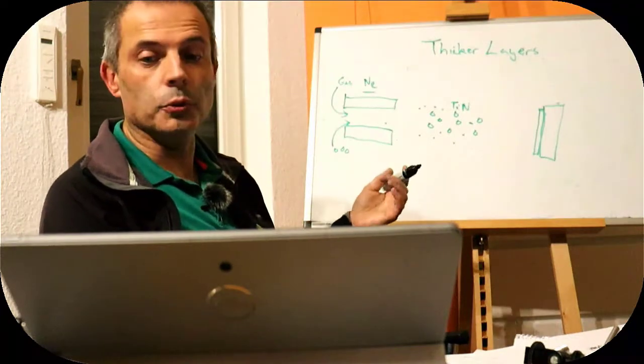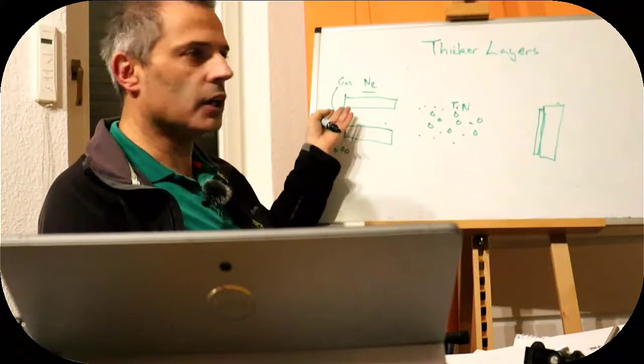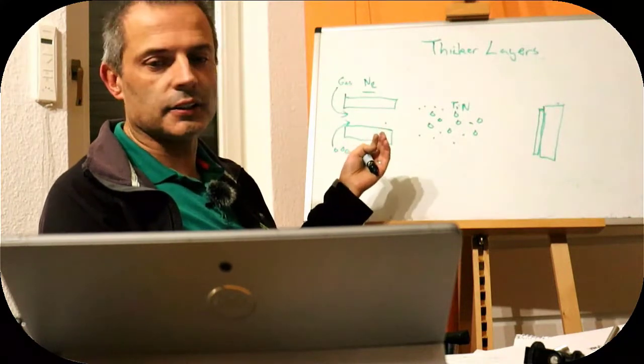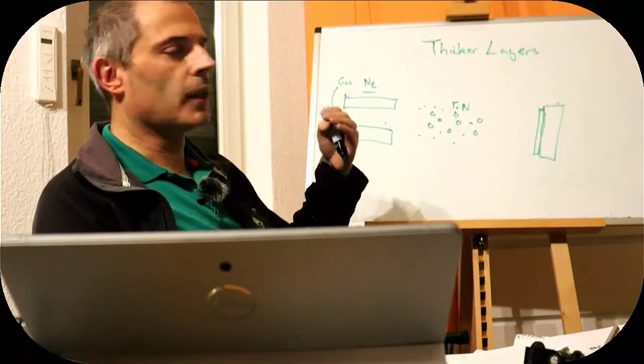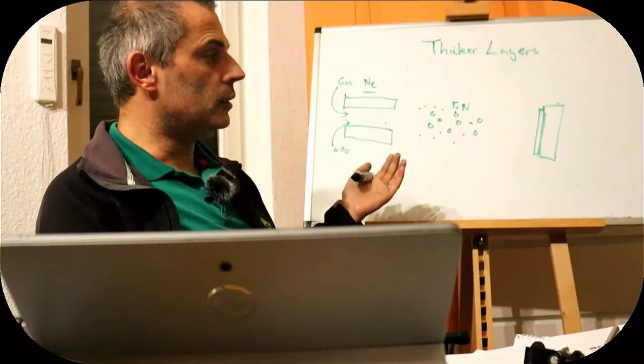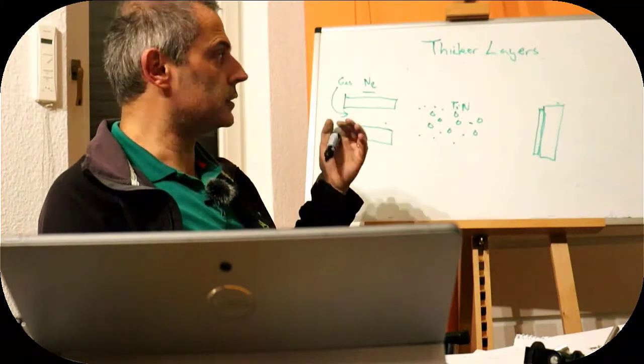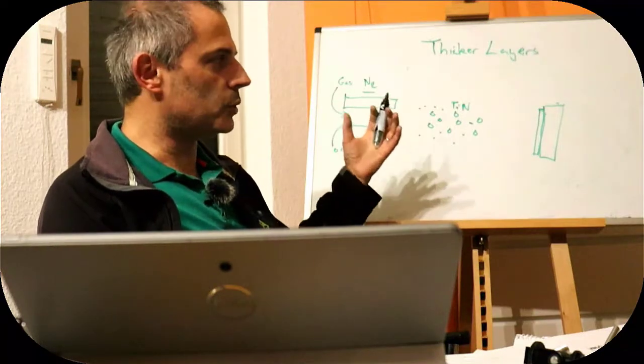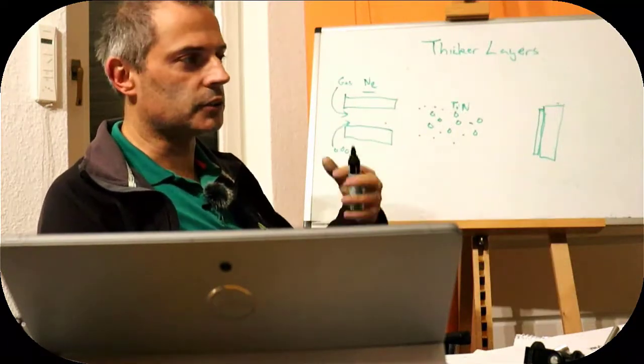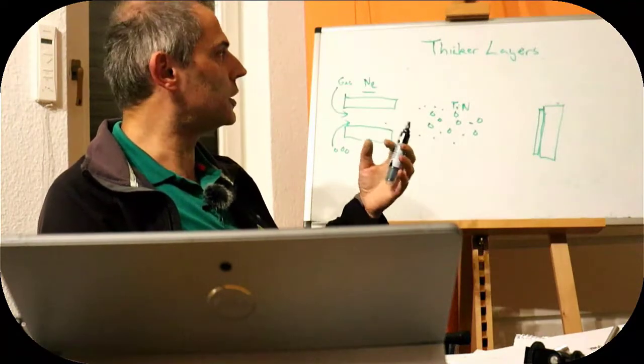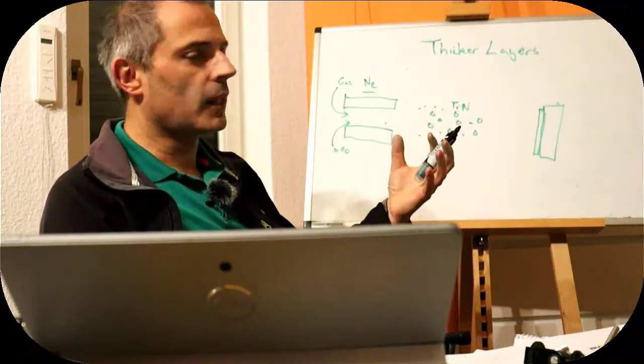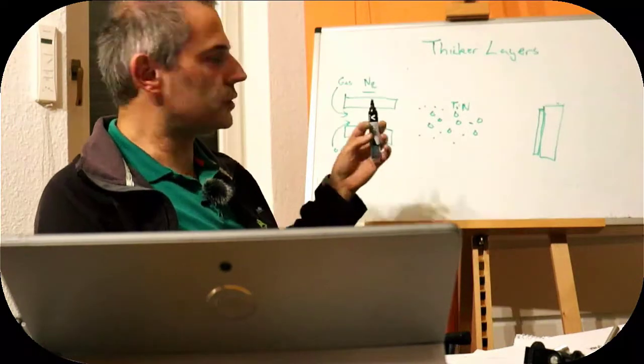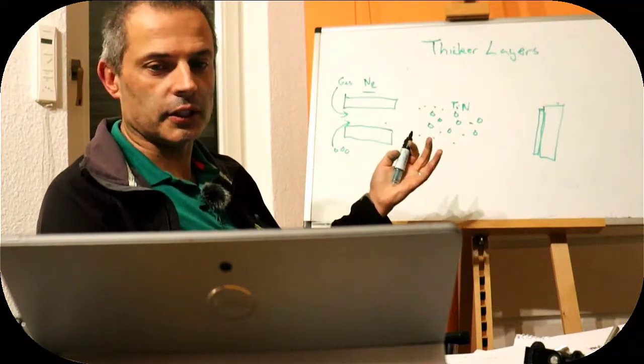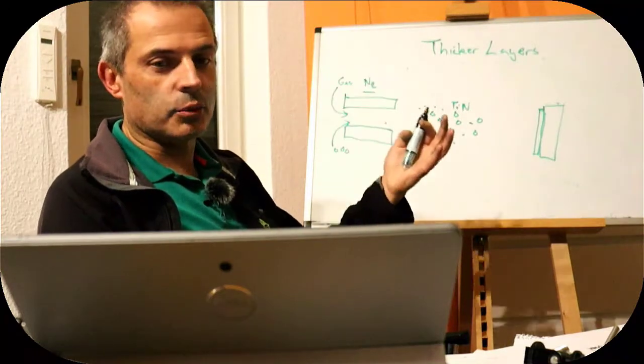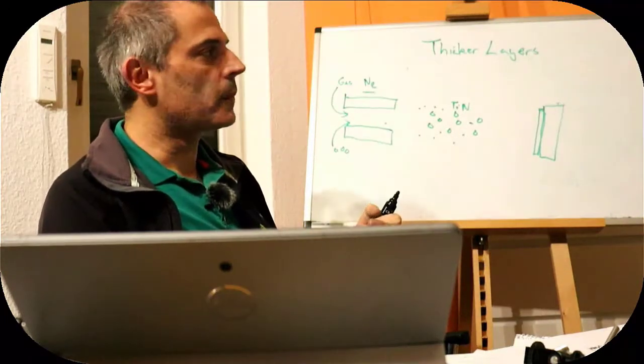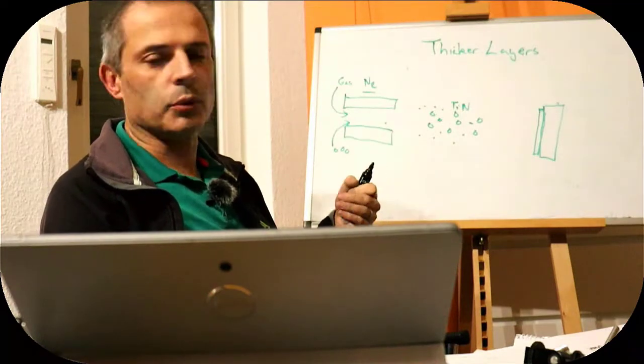So typically you would have thought, looking at this, what we want is argon in our gas, and that is a terrible gas for this. If you know anything about launching things into space from guns, or high-speed guns, multi-stage guns to get very, very high-speed projectiles, you will know that one of the problems is that the speed of expansion of the gas is the speed of sound in the gas, and so if we have a gas that's too heavy, then the speed of sound is lower, and then we have a bit of a problem.